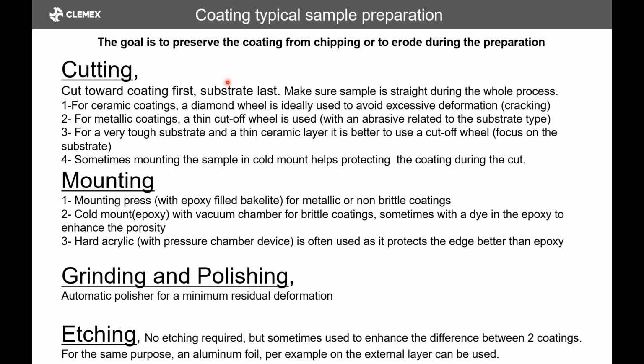And it sometimes helps to mount the sample before cutting it. Some samples are too fragile, and mounting them first and then cutting them afterward will help protect them. So you could use a mounting press. A mounting press is for non-brittle coatings. If you put a ceramic in there, there's a chance that the pressure will crack the coating. So normally for ceramics, you would use cold mount.